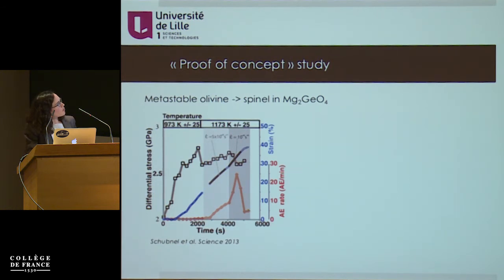So we compressed the sample and deformed it to get some stress on it at some temperature, and then we heat it to cross the transition. When we crossed the transition, the acoustic emission rate increased and even accelerated, and eventually we got a stress drop and an increase in strain rate, and that was a sample failure.